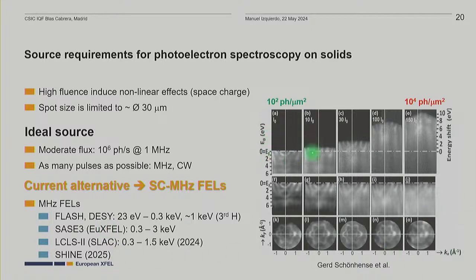So if you have on your sample something in the order of 10 to the 2 photons per micron square, you will be able to measure the band structure and the Fermi surface of your material. As you start increasing there, due to this nonlinear effect, you will have distortion on the spectra, and then at this limit of 10 to the 4 photons per micron square, which corresponds to 150 I0, the shape of your valence band is completely distorted, and the Fermi surface is distorted. You can correct this, of course, but when you do a pump-probe experiment, you want to make sure that you start with a well-defined ground state, because it might be that this could be also induced by your pump. And so in order to do this, what you need is to have a source with moderate flux, but with as many pulses as possible.